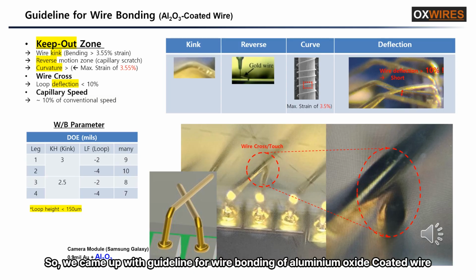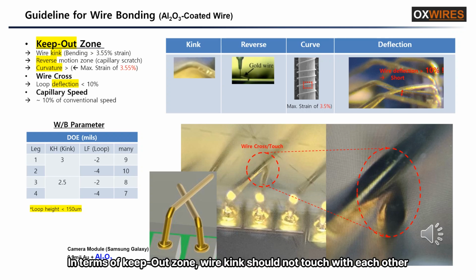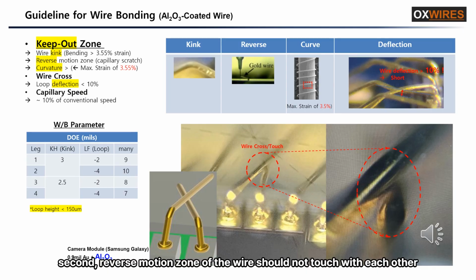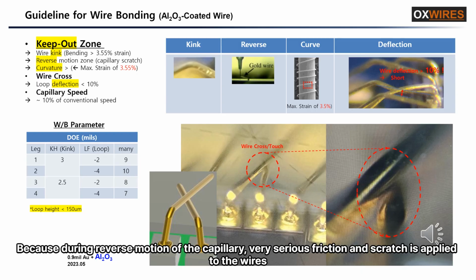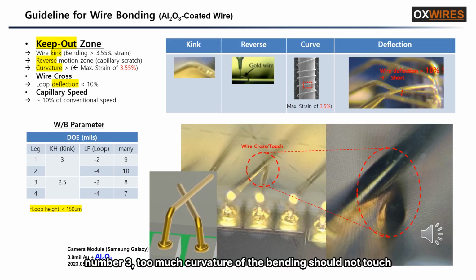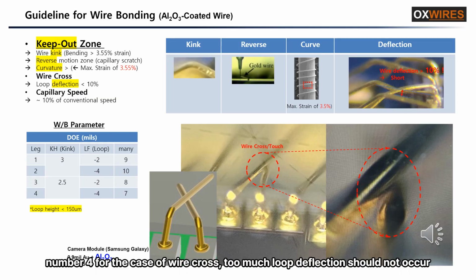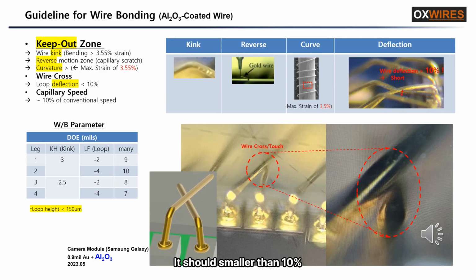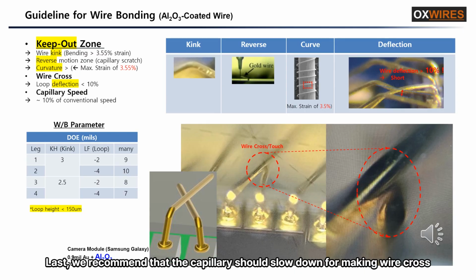So, we came up with a guideline for wire bonding of aluminium oxide coated wire. In terms of keep out zone, wire kink should not touch each other. Second, reverse motion zone of the wire should not touch each other, because during reverse motion of the capillary, very serious friction and scratch is applied to the wires. Number 3. Too much curvature of the bending should not touch. Number 4. For the case of wire cross, too much loop deflection should not occur. It should be smaller than 10%. Last, we recommend that the capillary should slow down for making wire cross.